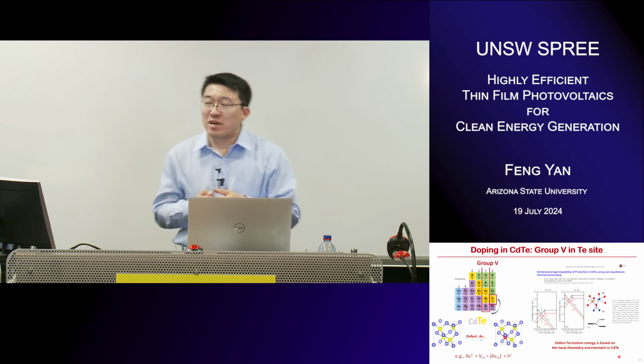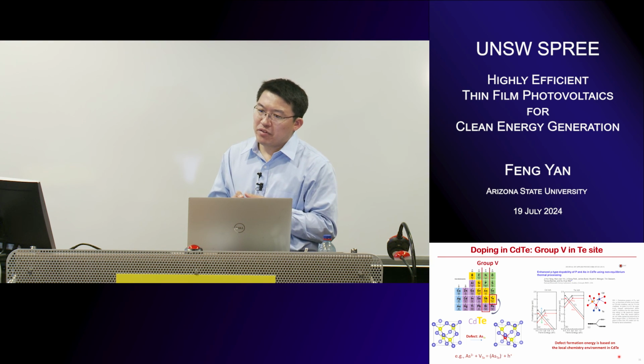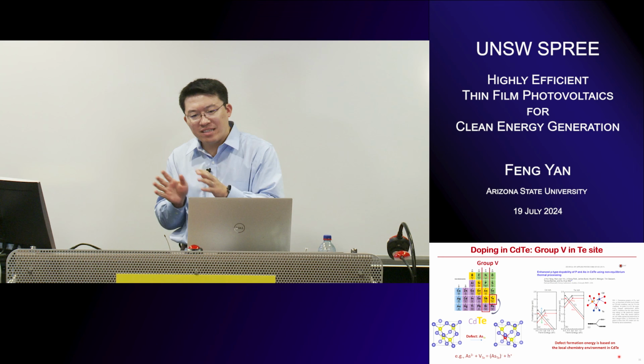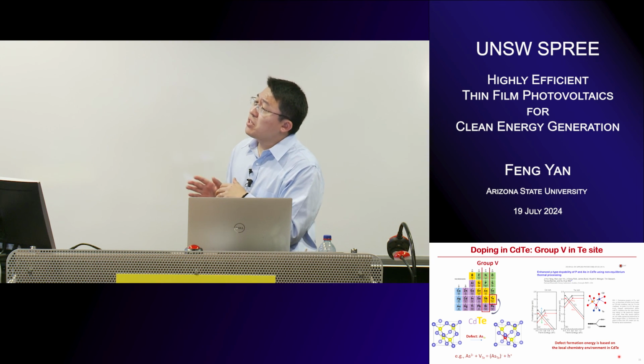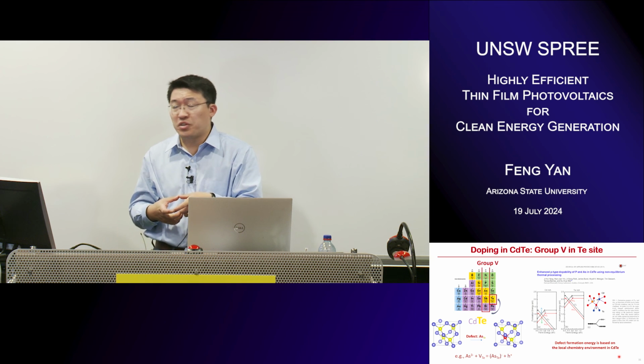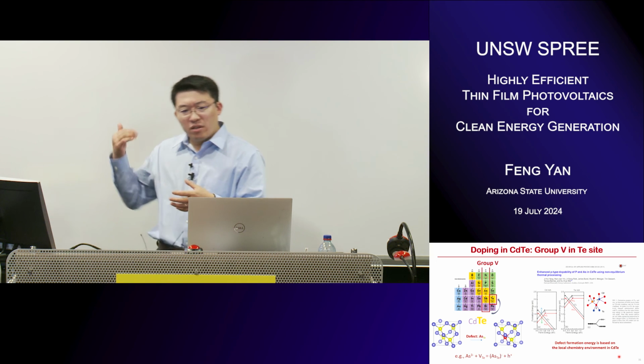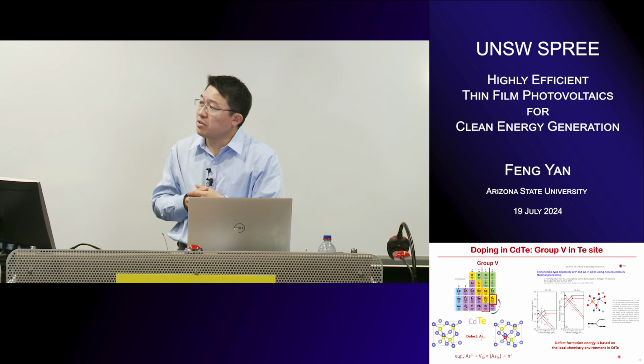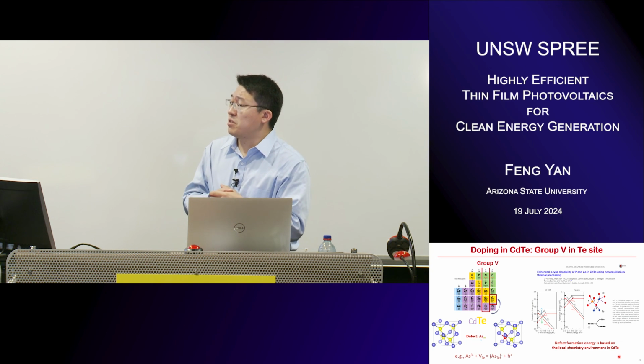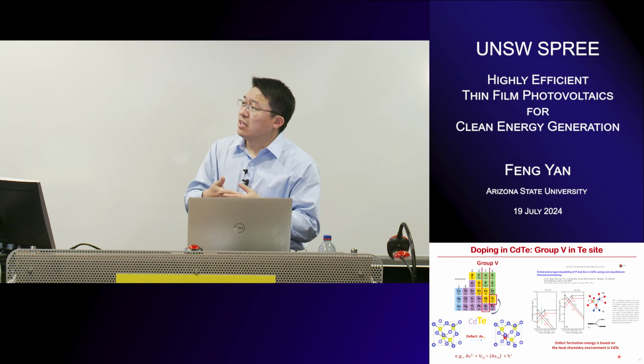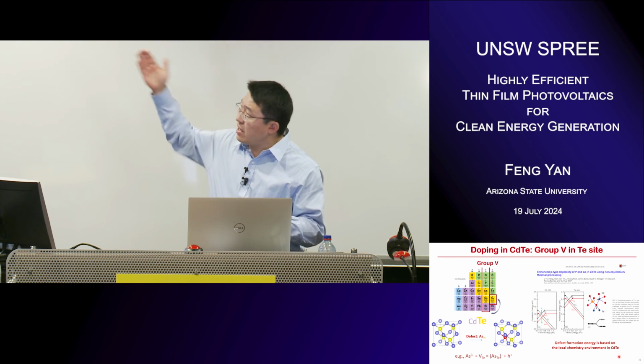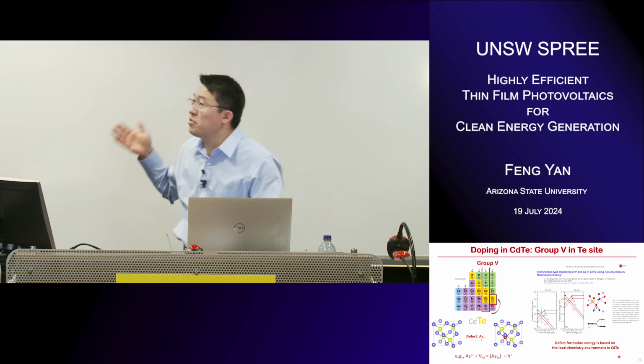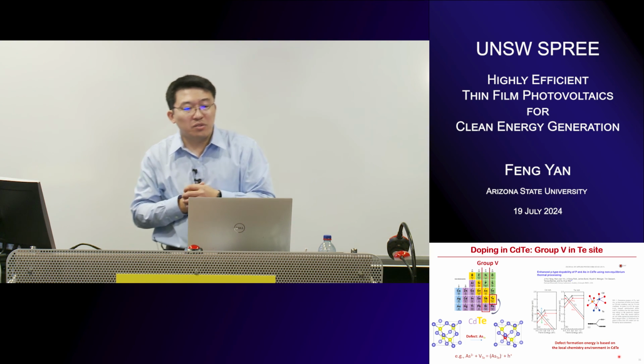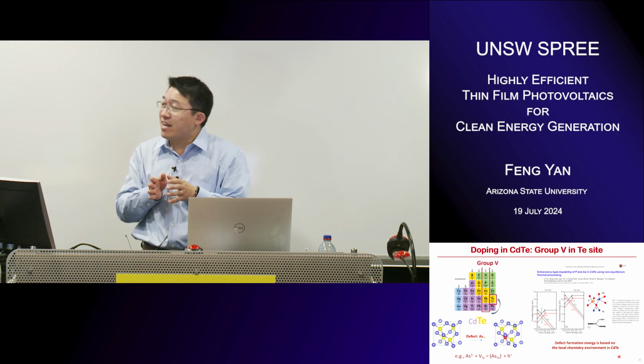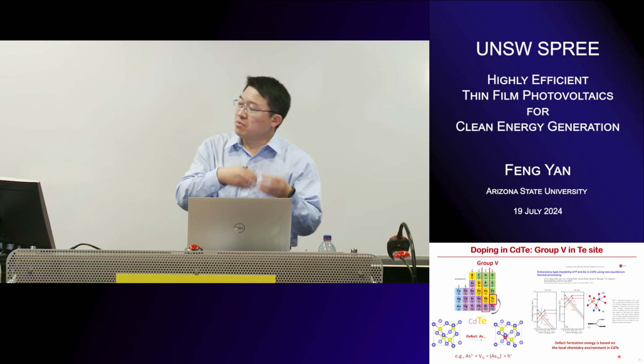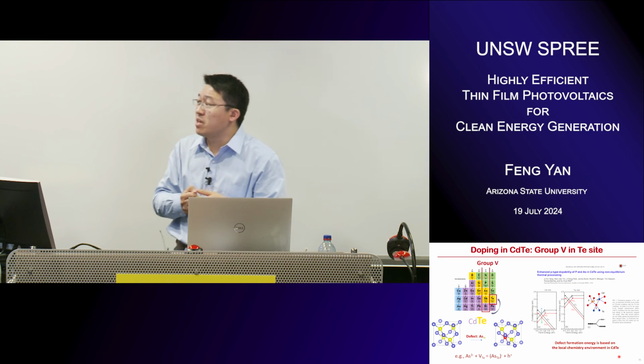Yes, not in my group, but this was documented previously by maybe five people. I cannot remember exactly. They did both polycrystalline and single crystal, because cadmium telluride can be purchased as a larger single crystal. But the challenging part, as mentioned, is that the single crystal needs a high temperature, about 500 or 600 degrees C, to drive this. That's true, the heavier the element, the more difficult the diffusivity. That's why, to drive the element to segregate from the grain boundary into the grain interior, we need to tune the processing window.